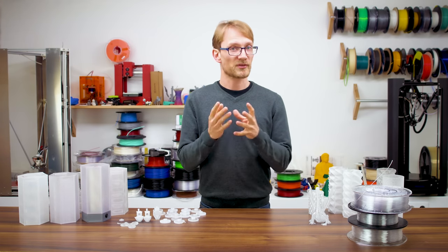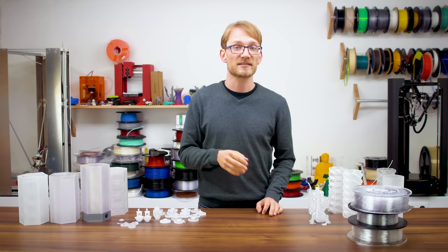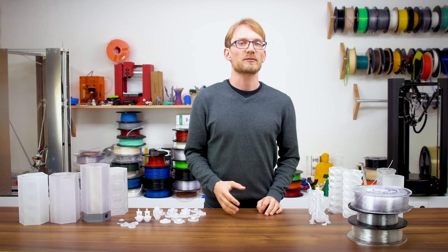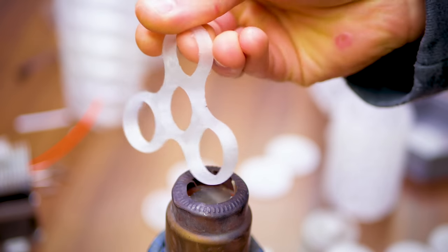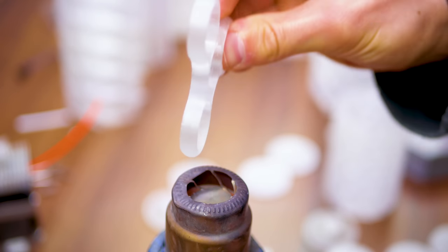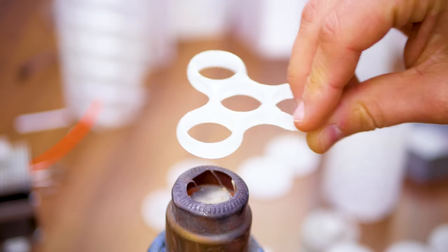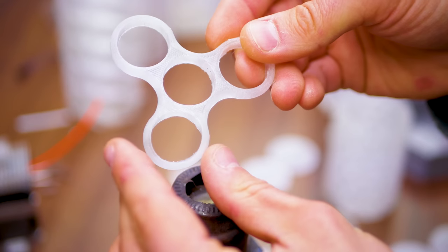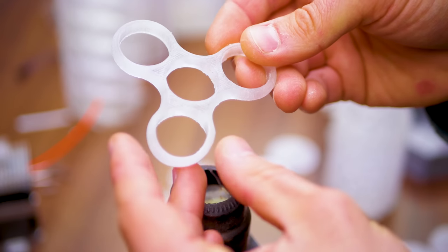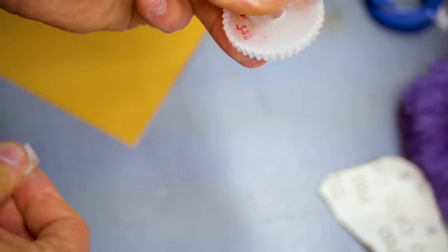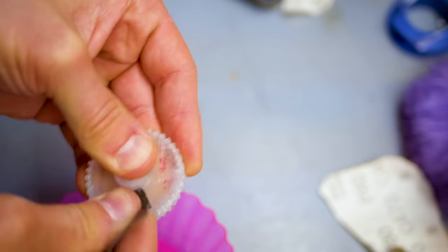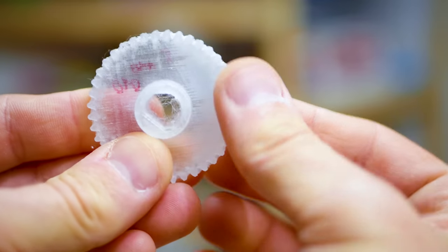I also tried to improve the surface by either flame polishing with a hot air gun set to 600 degrees or sanding it beforehand, but with the hot air gun, the surface started bubbling up and softening before it started getting more transparent, so that part's gone. And when I tried to sand a part beforehand, yes, it ultimately did get a bit clearer, I think, after I heated the surface that was sanded to 1200 grit, but again, it's really hard to find that optimum spot where the plastic neither bubbles nor softens too much.